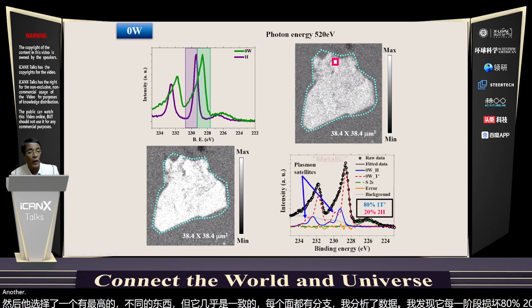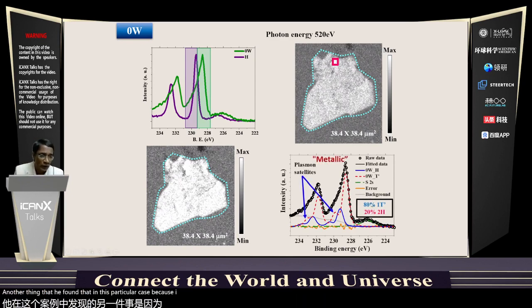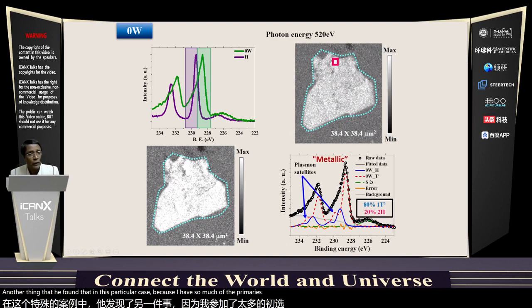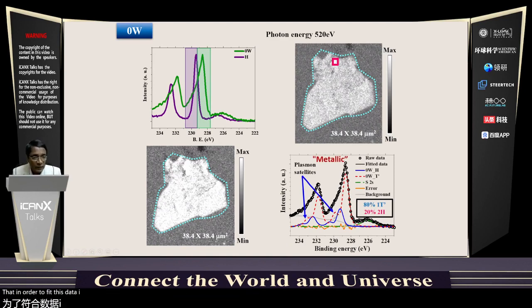Another thing that we found in this particular case, because I have so much T prime phase, is that in order to fit this data, I needed this bump, which I didn't need before. This bump actually comes from a plasmonic satellite, indicating some kind of free electron response in the system. And that's when it is showing up. Keep this in mind, it will become important in a moment.